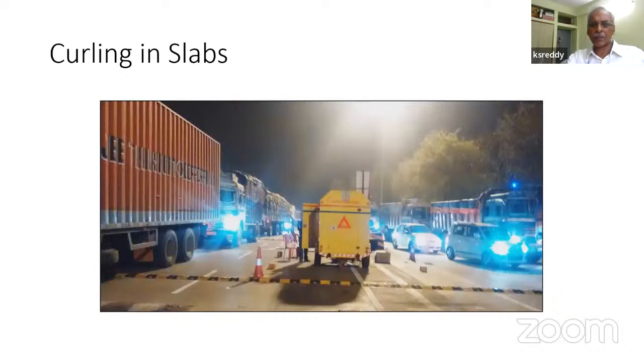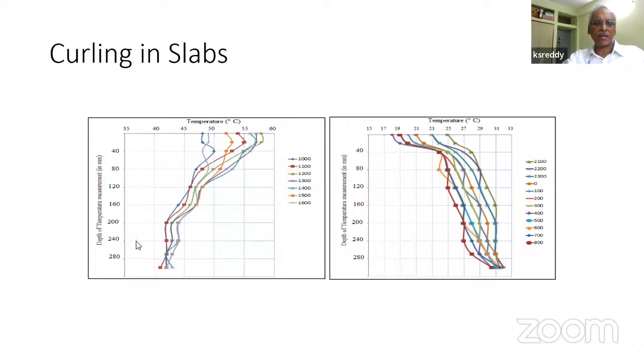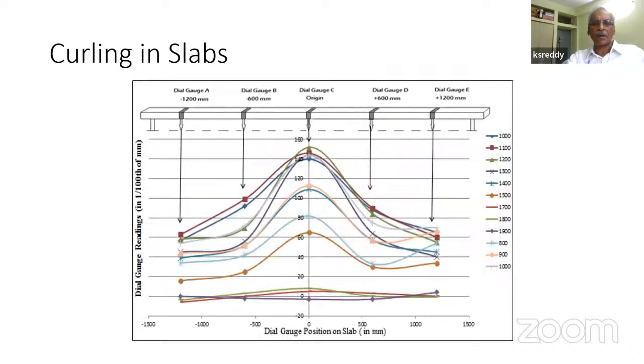We set up this experiment near a toll booth. And these are the variations of temperature profiles at different hours of the day, daytime as well as nighttime, positive and then negative temperature gradients. This is the movement of the curling of the slab, up and down at different hours of the day. What is depicted is the daytime movement during different hours. There was one time at which the slab was almost flat and then it starts lifting up. This is an exaggerated figure. The slabs don't lift up by that much, but the fact is that slabs would actually lift up and down during the course of the day.